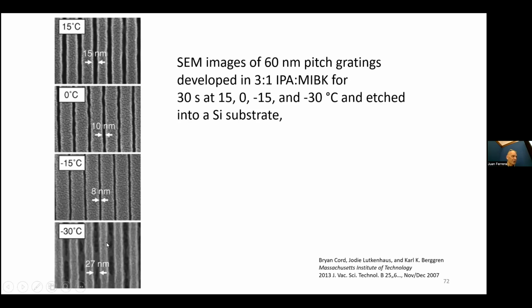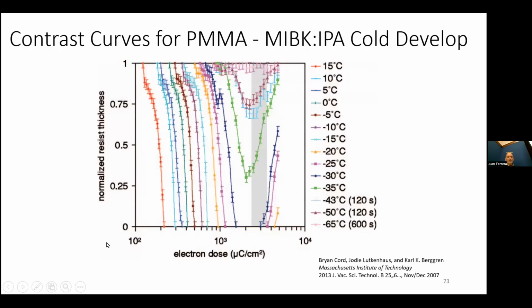And then if you go to minus 30, it's terrible. And the reason for that is this. This is a very complicated plot. I suggest you look at it later and study it more if you're really interested. What he's showing here is this aquamarine line here in the middle corresponds to minus 15, and that's optimal. It's optimal because this thing is as close to vertical as any of the lines in this chart are.